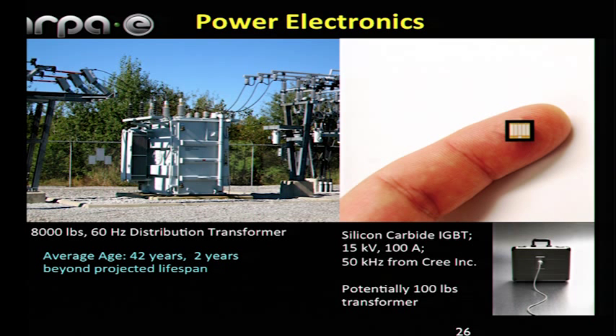Now, this is the heart of this system. You take these transistors, put them in bridge circuits, whether you have 4 of them or 6 of them, depending on the number of phases, and you have these LC filters, and now you have power conversion that can happen. And if they operate at 50 kilohertz, the size of the transformer could potentially be 100 pounds in weight, and it becomes smarter. So that's the technology. No one has really built a transformer yet electronically, and that's what's going on right now.